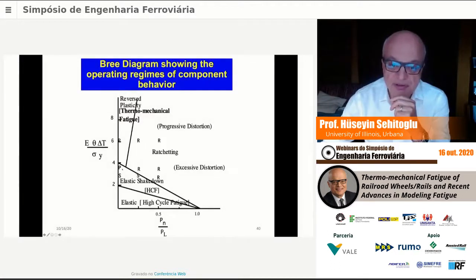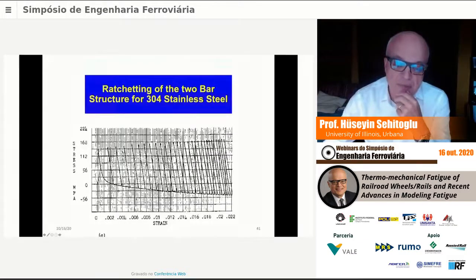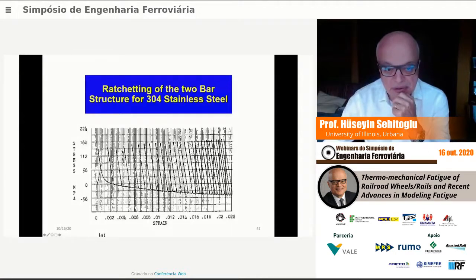These are experimental results. These boundaries are shown here based on some simple predictions, of course. P means you're getting plasticity, S means you're getting shakedown, and E means you're getting elasticity. So the ratcheting means something like this. You plot stress against strain, and this is the cooling, and then heat, cool, heat, cool, heat, cool, and this just keeps going.